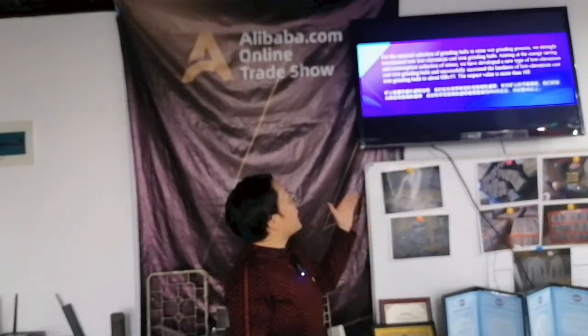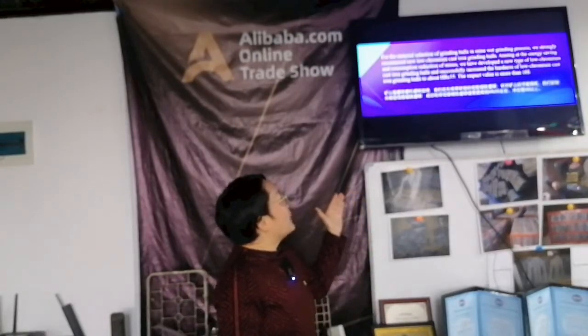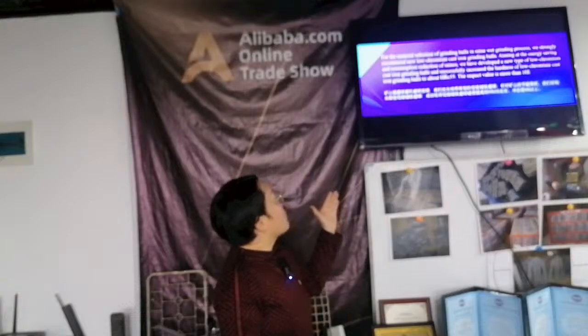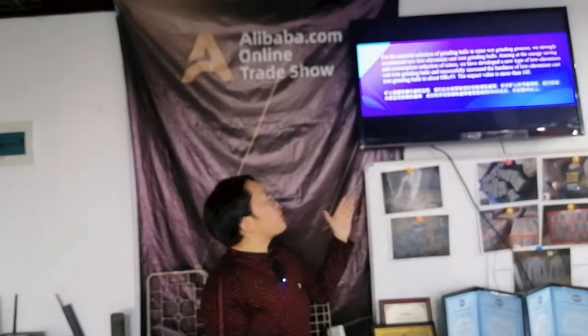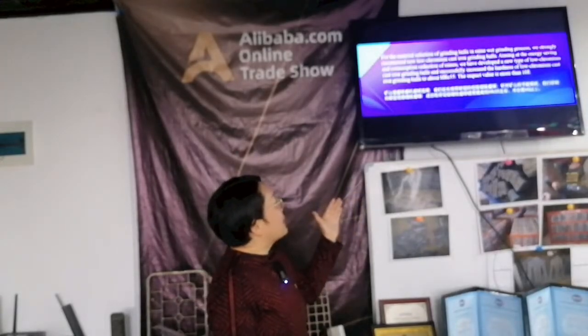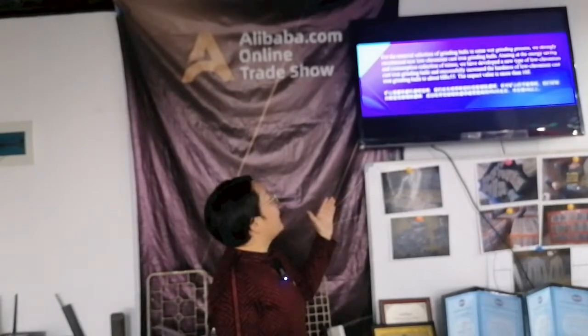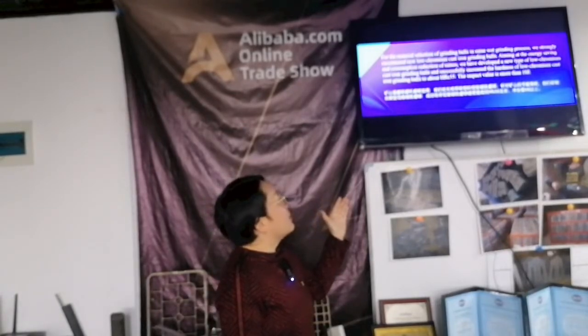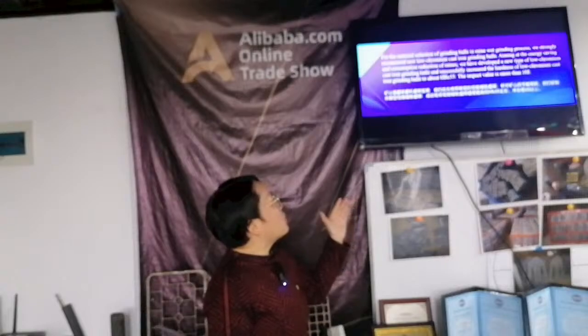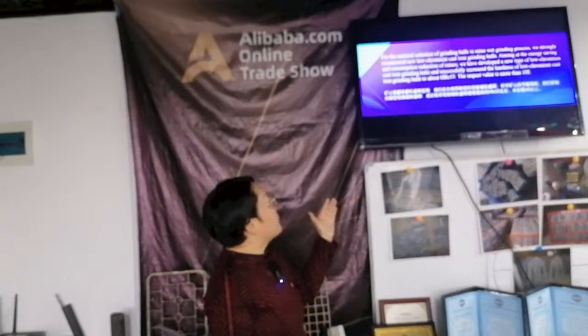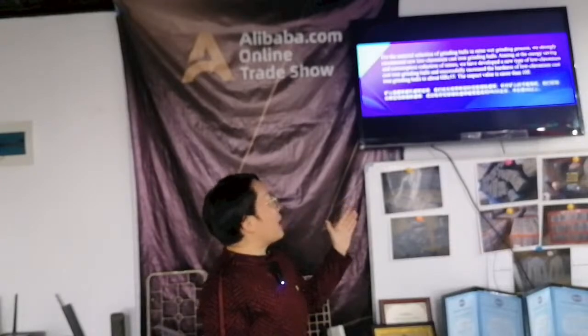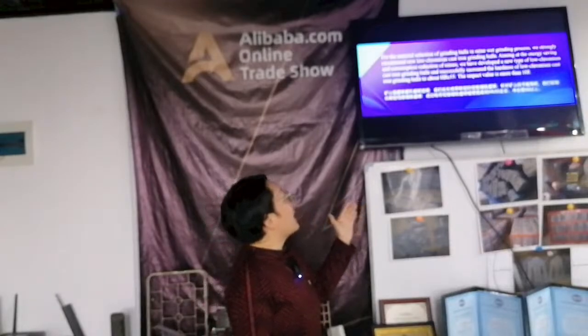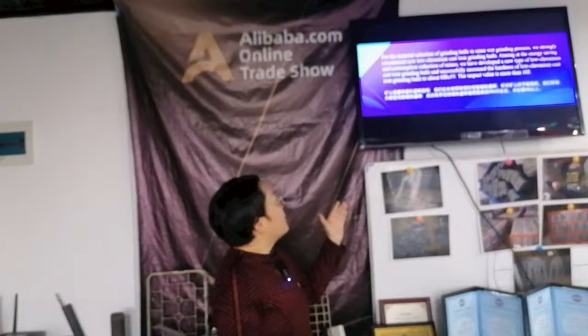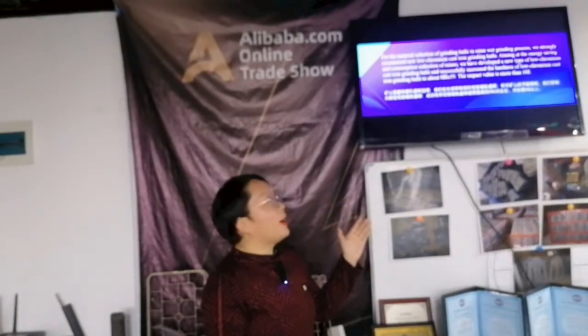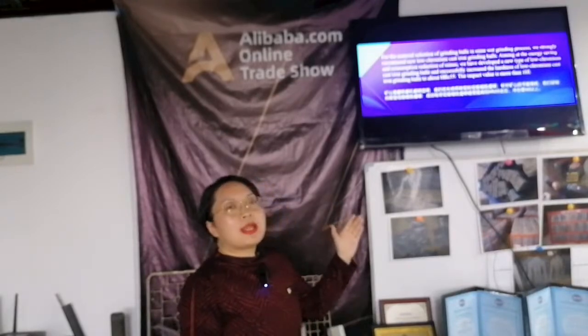For the material selection of grinding balls in the mine wet grinding process, we strongly recommend new low chromium cast iron grinding balls, aiming at the energy saving and consumption reduction of mines. We have developed a new type of low chromium cast iron grinding balls and successfully increased the hardness to about HRC 55. The impact value is more than 10 J.